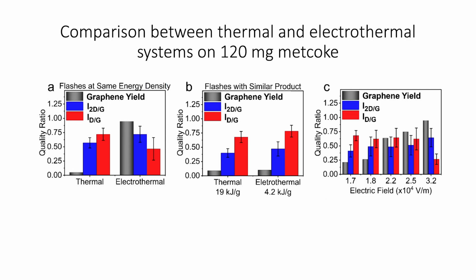If you look at the comparison, this is still 120 milligram samples in both of these reactors. If you just do it thermally, flashes at the same energy, here's the graphene yield. This is what you get sitting on top of a carbon paper. This is what you get if you're driving a current through it. So it is truly an electrothermal process, not a thermal process. If you want to get flashes with similar product constituency, thermally you have to put in 19 kilojoules per gram. Here you put in 4.2 kilojoules per gram. And here you can look at the electric field: as it starts increasing through the sample, you get better and better graphene.